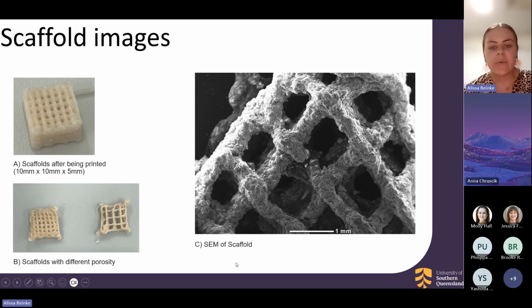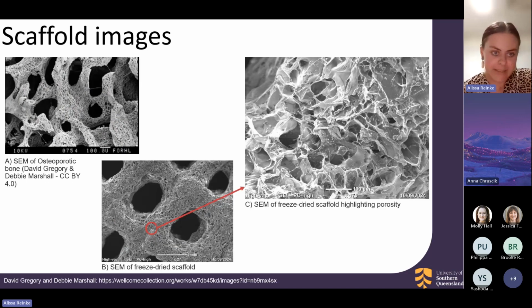When completing SEM of the scaffold, you can see that it is quite a rough surface. Now, this is ideal for cell culture because it gives the cells something to actually grab onto to adhere and start growing. And also you can see the pores were maintained that the printer created. Now, some very recent data, recent as in within the last 24 hours, I have found that freeze drying the scaffolds instead of evaporating the binder results in better porosity.